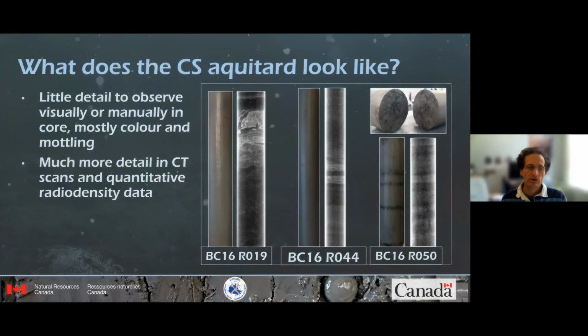So what does the Champlain Sea Aquitard look like? Well, here we have a naked eye view. These are photographs taken just after the core was extruded and scraped off. And next to them are the CT scans of the same cores. What you see is not untypical of the Champlain Sea. There's not a lot to see, really, except the most frequent descriptions are color banding, or mottling. Sometimes there are descriptions of stiffness, and sometimes you can see the coarser laminations, and especially if you let the core dry out, then you start seeing differences based on grain size as well. But we didn't let anything dry out, and we often used the CT scans to guide our subsampling.